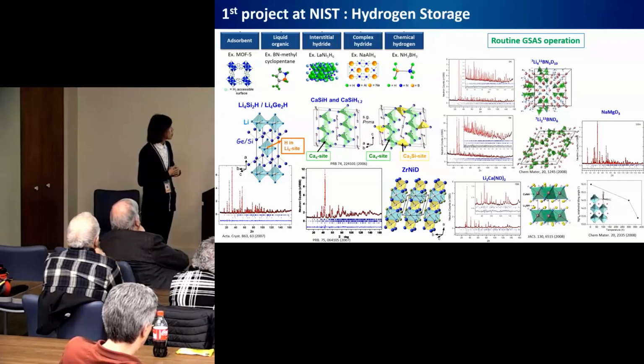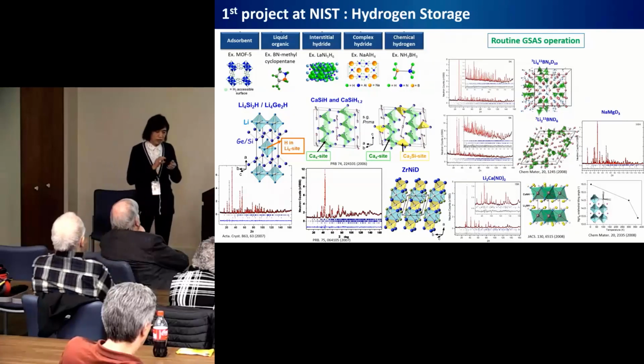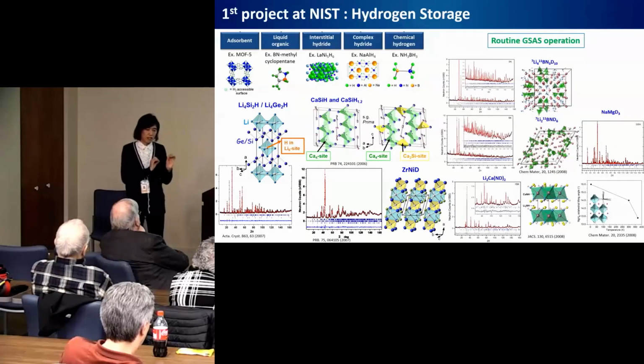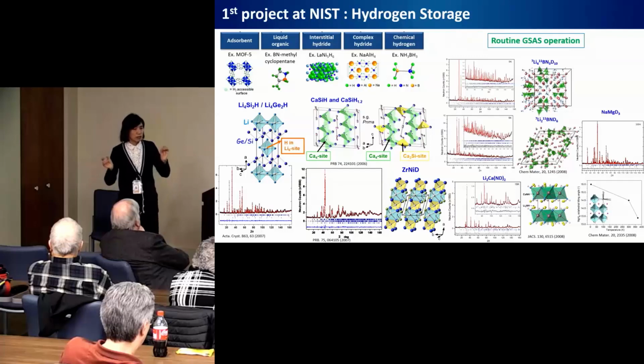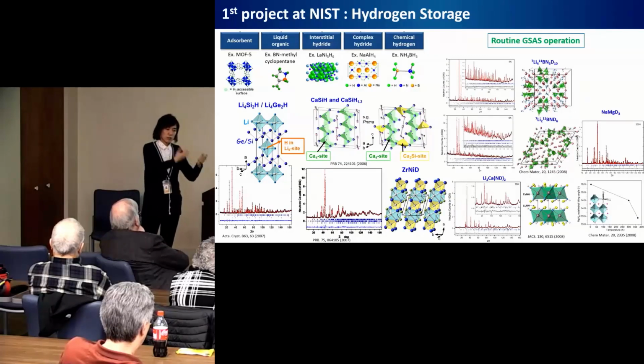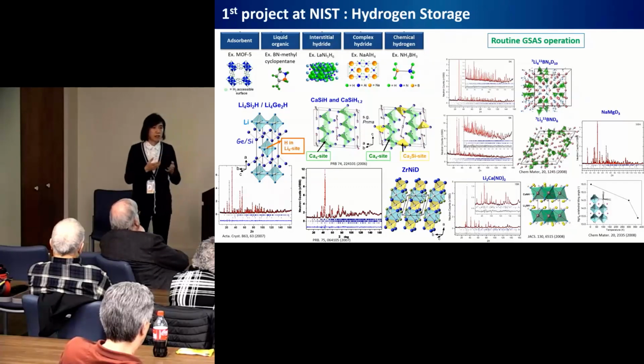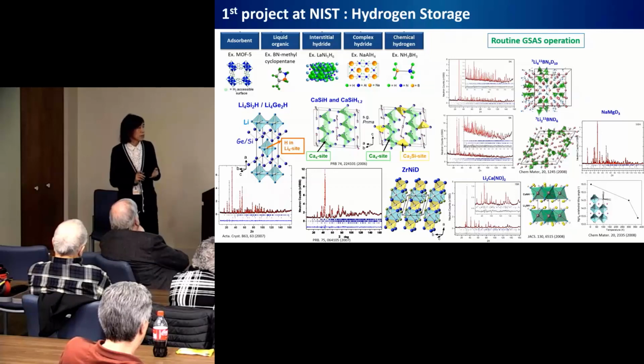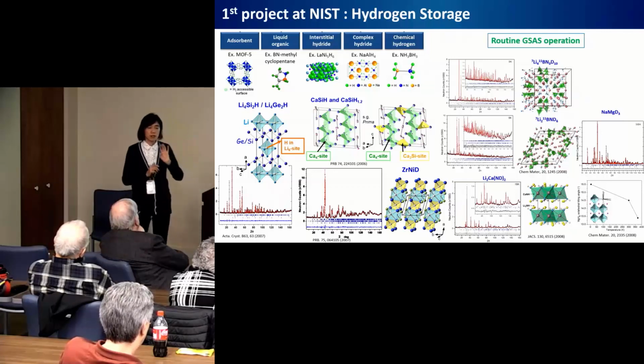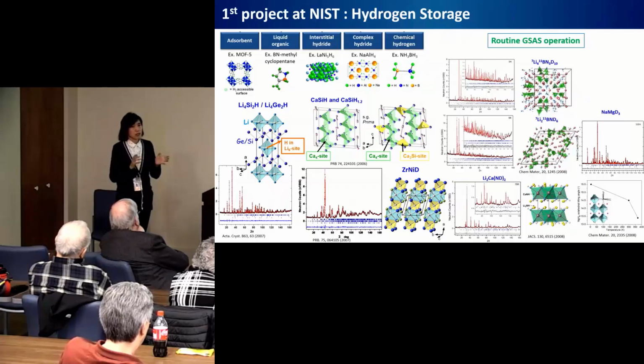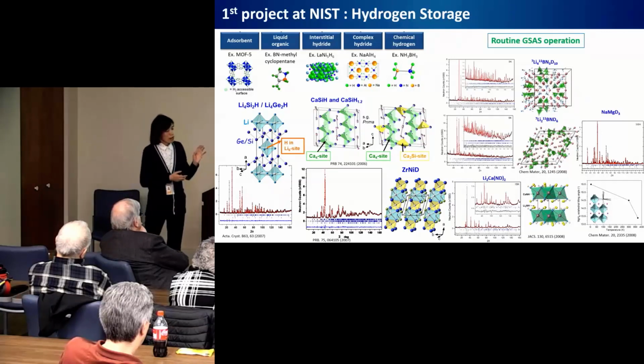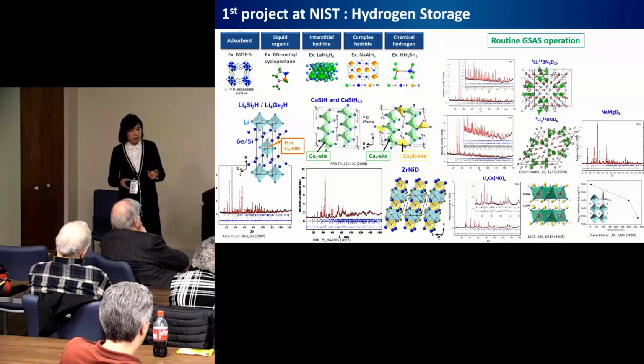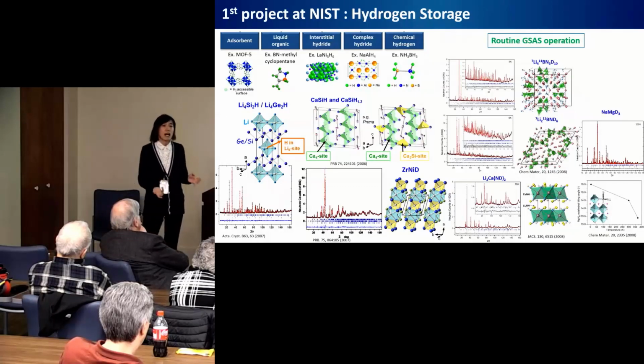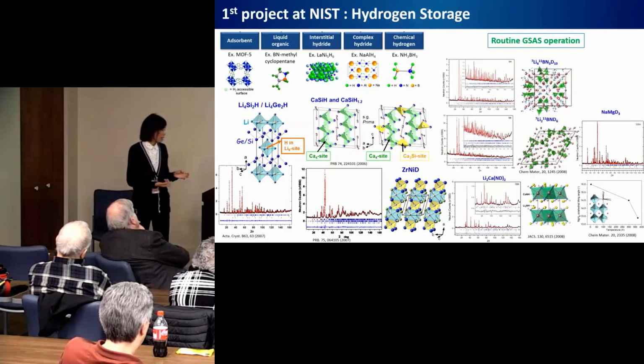For example, in those interstitial metal hydrides, the interaction between the hydrogen atoms and the metals is relatively weak. So the materials can release and absorb hydrogen at relatively low temperature. However, the hydrogen content of these materials is still not sufficient for practical hydrogen storage applications. So I wanted to work on systems with higher hydrogen capacities and lower dehydrogenation temperatures.